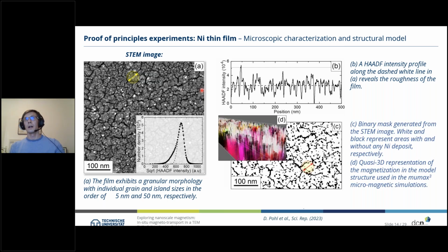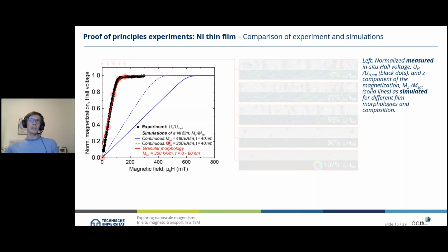So we thought, okay, let's use that information to generate a binary mask in order to simulate now this different behavior of the coupling of the different grains, to understand in more detail how the magnetization now changes when we have such a pattern instead of a continuous nickel film. And if we assume the granular morphology and only slightly reduce the saturation magnetization due to oxidation of the film, then we have a nice fit of the simulation and our experimentally measured Hall voltage.